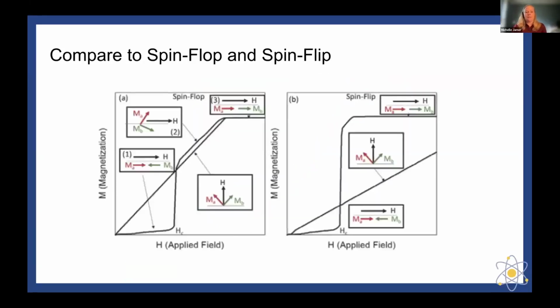So we can compare this to a spin flip and a spin flop. If you were to look at the schematics for the spin flop, what you see is if you have an applied field, you'll have a critical field at a certain magnetic field where all of a sudden you'll have a drastic increase in the magnetization, and then you'll have this spin canting effect. If you were looking at it along the opposite direction, what you'll see is that it behaves similar to the C axis, where you have the applied field, where it behaves linearly up until an inflection point where it becomes saturated. Spin flip looks somewhat similar. It's just based on how your transition is actually ordered, whether or not you have extra inflection points from the spin flip to the spin flop.